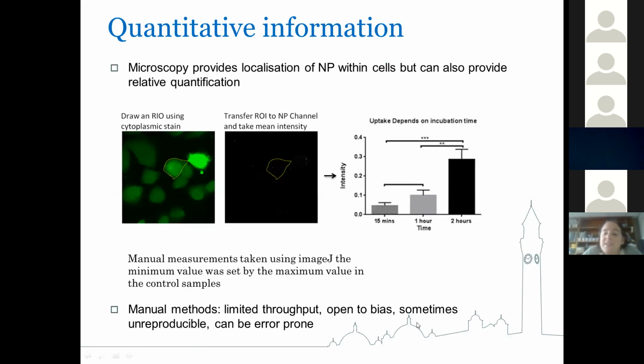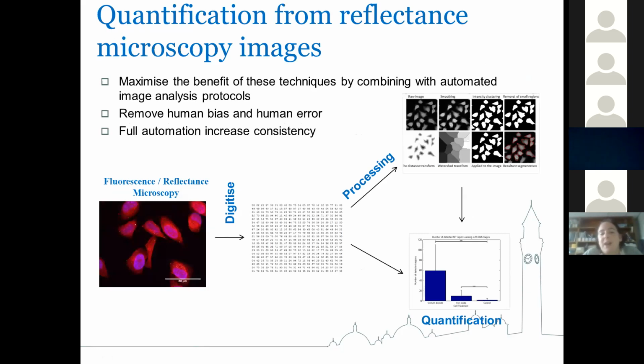So we were first able to do the counting manually, but that was obviously slow and could be a bit irreproducible and error prone. So we also then developed some algorithms to automate the process. So we take the images as we got them, we digitize them, then do some processing in terms of identifying the region of interest. We'd remove any cells that were only partially in the image, do some changes of thresholding and so on, and then get to the quantification of the nanoparticle uptake.